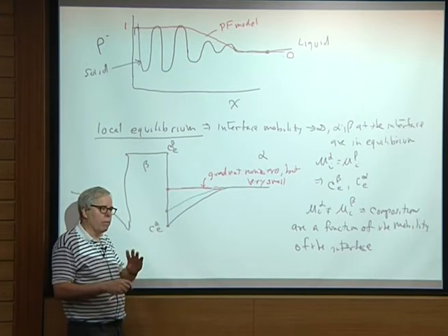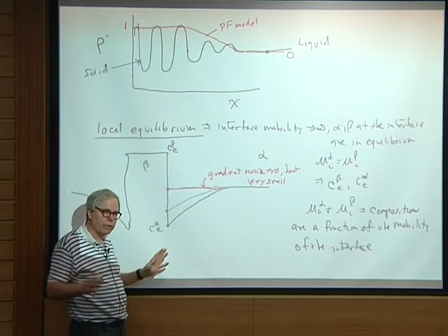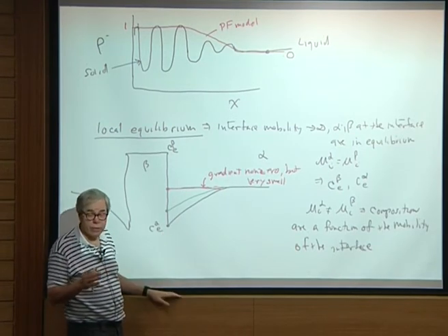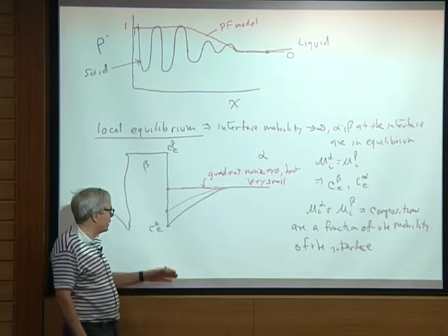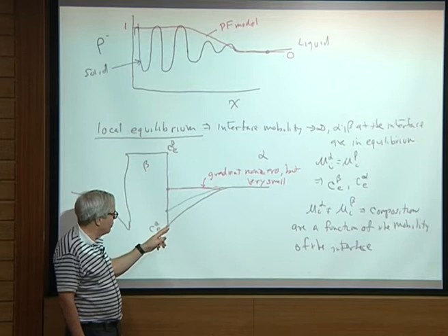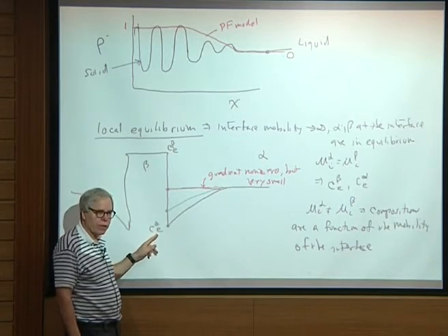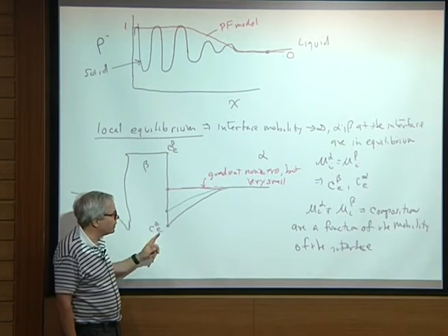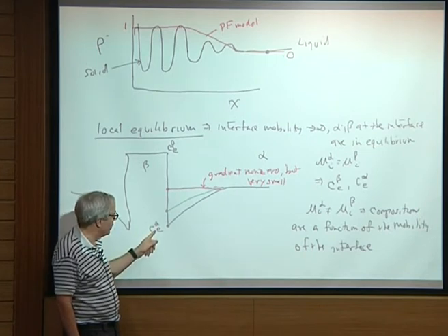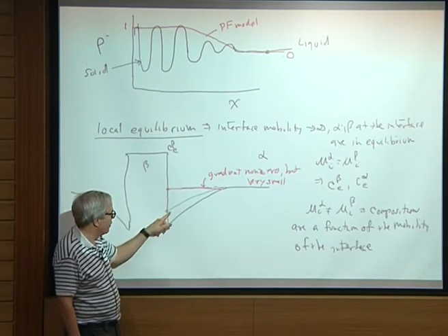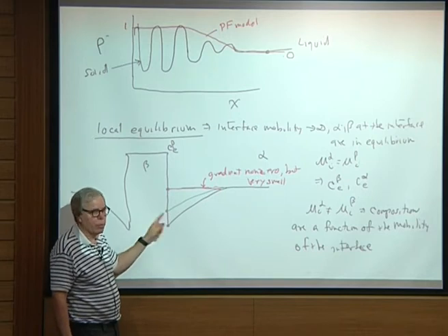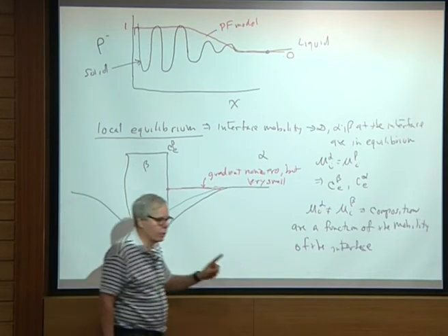However, in a vast majority of phase transformation problems, in solid and liquid transformations, for example, solidification at reasonable rates, solid state phase transformations at reasonable growth rates, this local equilibrium approximation is a very good approximation. And you want your computational model to give you these equilibrium compositions, not this thing that's a function of the mobility. Okay?